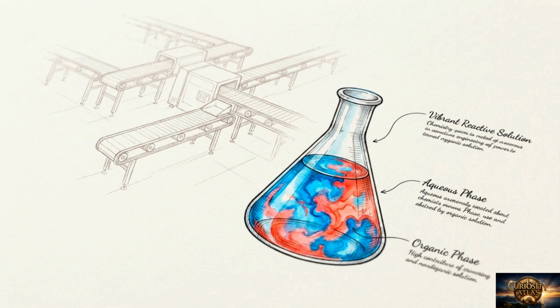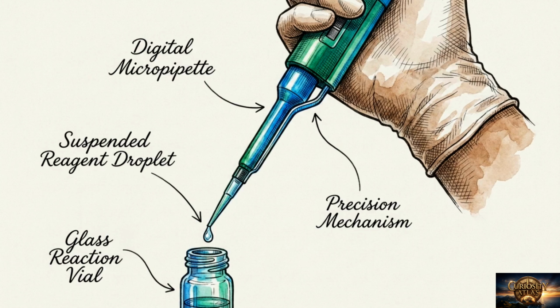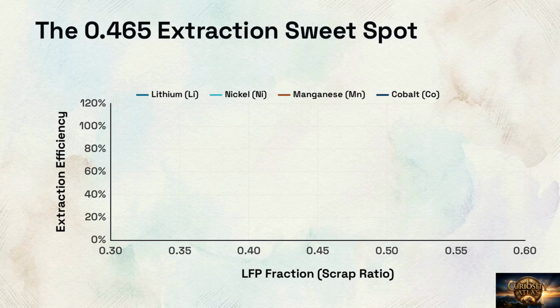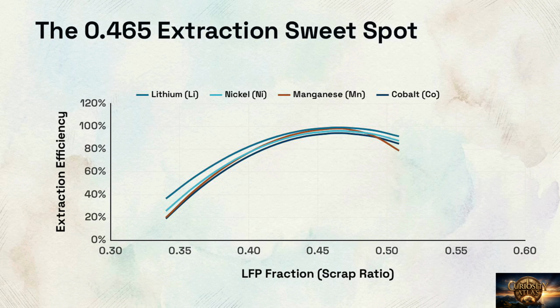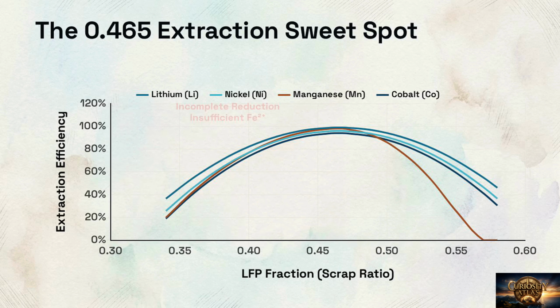But relying on this internal reaction requires a very precise mathematical balance. This chart tracks the extraction percentages of lithium, nickel, manganese, and cobalt as they relate to the fraction of LFP added to the feed. On the left side of the curve, below an LFP fraction of 0.47, the extraction is incomplete. The recovery fails here because there is simply not enough iron 2 available to reduce the full volume of NMC. However, if the LFP fraction rises above 0.51, the yields collapse just as sharply.